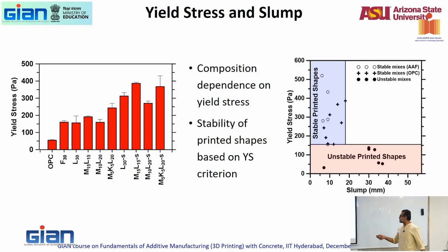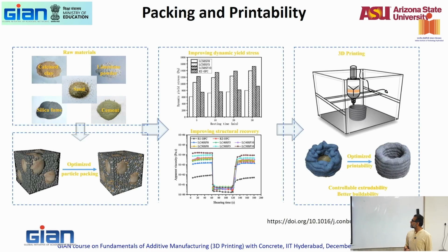And then if you do yield stress as a very quick measure, and slump as a very quick measure of can I print or not, this is what you get. At very low yield stresses, you really can't print. But at lower slump values and higher yield stress, you get some stable printed shapes. Again, trial and error way that you can get it, and you can relate yield stress to slump.